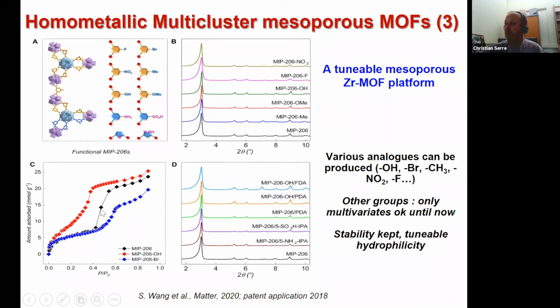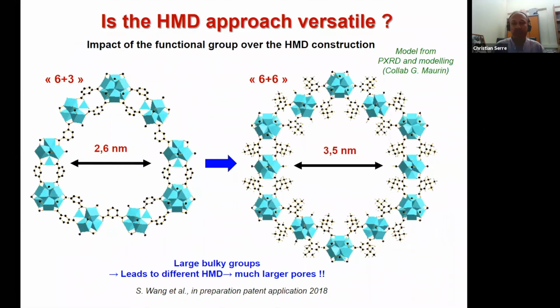And as an example, here you see the water sorption isotherm on the left. You see that if you introduce a bromo-OH group, you can shift the water sorption isotherms quite significantly, which means that at the end, we really have the possibility to have mesoporous MOFs with very significantly different surface chemistry. And this is a result that has not been published yet.